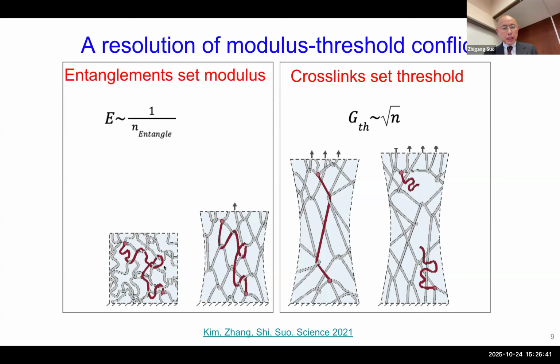If you have a lot of entanglements, you can see that the entanglement also gives you modulus, right? The number of monomers between two entanglements actually sets the modulus. The number of entanglements sets the modulus. So if you don't break any chain, all the entanglements resist deformation. They're good guys. However, before you break any bond, the interaction between entanglements is non-covalent. It's very weak in the rubber. It's a liquid-like interaction between the non-covalent bonds.